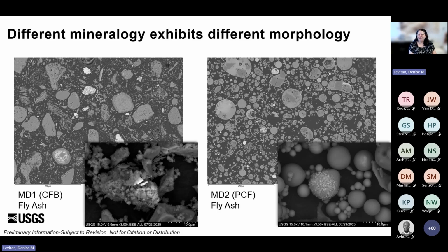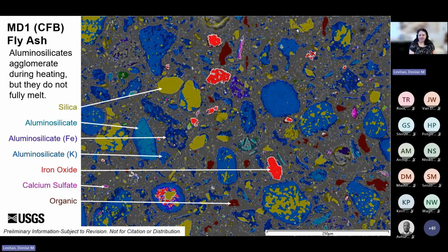So this again illustrates that, although earlier we determined that they do have pretty similar overall chemistry, here we can see they have really different morphology, indicating those different mineral phases present that we saw from the XRD results. So we're going to tie together now that chemistry and the morphology. So this is the same image, the background upper image of MD1 from the previous slide, but now it's been scanned with energy dispersive X-ray spectroscopy, or EDS, to identify what elements are present. So then each element or combination of elements has had a color applied so that we can see what particles are made up of what chemistry.